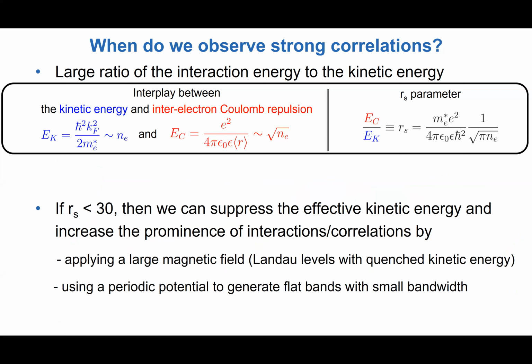And there are two ways to go about this. The first one is what the community of scientists working with gallium arsenide have pursued, which is to apply a magnetic field that is perpendicular to the plane. And what the magnetic field does is that even though the bands are very dispersive initially, you end up with flat Landau levels. And once you confine all the electrons into the lowest Landau level, the kinetic energy is gone. There is no kinetic energy scale, and the only energy scale to deal with is these interactions.